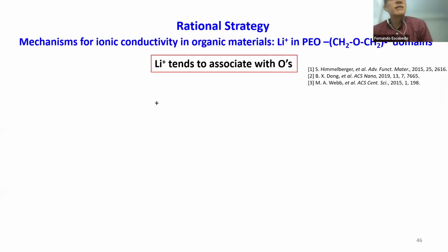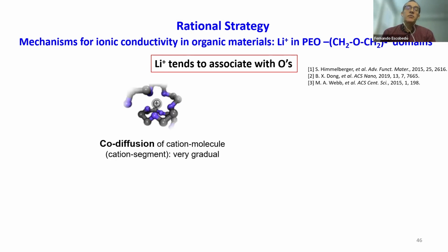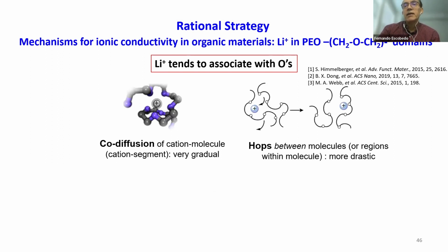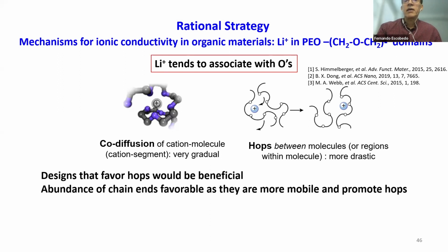So, what are the mechanisms by which this conductivity happens in these materials? The key observation is that the lithium ion tends to be associated with the oxygens in the ethylene oxide units. That's been known for a long time. Then the motion can happen by co-diffusion, where the cation and the molecule it's associated with move together. That tends to be more gradual, but also via hops, where the ion moves either between two molecules or between two different regions within the same molecule. So these hops will be in some ways more drastic than co-diffusion. And co-diffusion depends on the whole molecule moving, which can be too slow. So for sure, the features that favor hops would be beneficial.